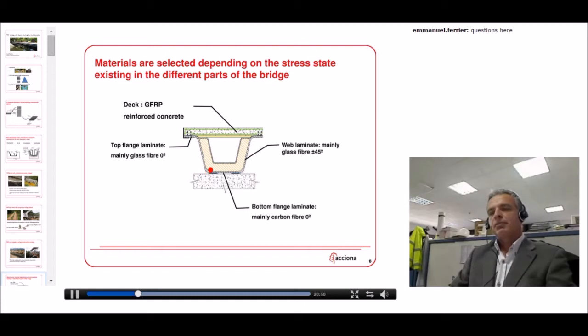But you can see from this picture that in our case, the bottom flange laminate is mainly made of carbon fiber at 0 degrees, while the top flange laminate is mainly glass fiber at 0 degrees, and the web laminate is mainly manufactured using glass fiber at plus minus 45. The reason for this orientation is obvious. Top flange and bottom flange resist mainly tensile and compression stresses induced by bending, so the fibers are aligned in the direction of the bridge, while the web resists mainly shear stresses, and for that reason fibers are oriented mainly at plus minus 45.